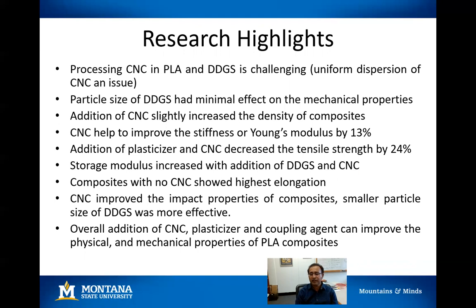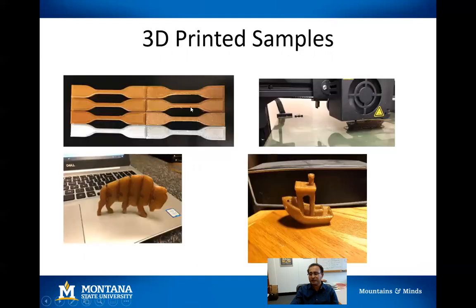The storage modulus increased with the addition of cellulose crystals and DDGS, and the glass transition temperature decreases when we add the plasticizer and the DDGS into PLA. The composites with no CNC showed the highest elongation in terms of strain. We also noticed CNC improved the impact properties of composites. The smaller particles were more effective in improving the impact properties compared to large size particles. Overall, from this study, we found that addition of CNC, plasticizer, and coupling agent can improve the physical and mechanical properties of PLA composites. So here are some of the pictures of 3D printed samples.